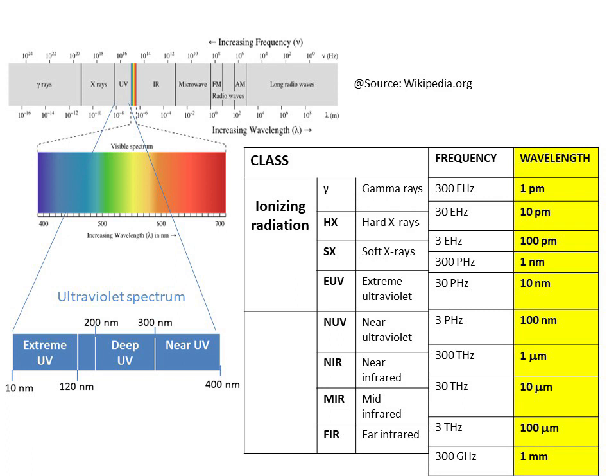These shorter wavelengths imply a high energy of light, and thus different sources to obtain the light from this part of the spectrum, and an increasing complexity of the optical systems, and also an increasing cost. It is important to note that the reduction in the wavelength of the light is not directly related with the reduction of the resolution size, due to the fact that there is a complex system involved in the photolithographic process. The resolution depends also on the optical systems — on the possible aberrations that can appear and the diffraction effects of the light — and also on the chemical characteristics of the photoresist, specifically whether the resist can or cannot replicate exactly the same sizes as the pattern of the optical mask.